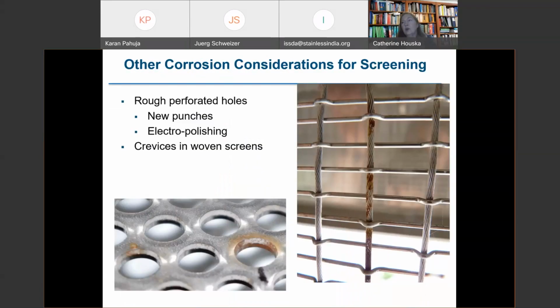When you are perforating stainless steel, there are a couple ways of doing it. One of which is punching, and I'm showing a picture of that. If the punches are not new, or where the stainless steel is too thick, you can get a rough, jagged edge, which can be a place where corrosion can start. Laser jet and water jet cutting are used as well. Those generally give a cleaner line.